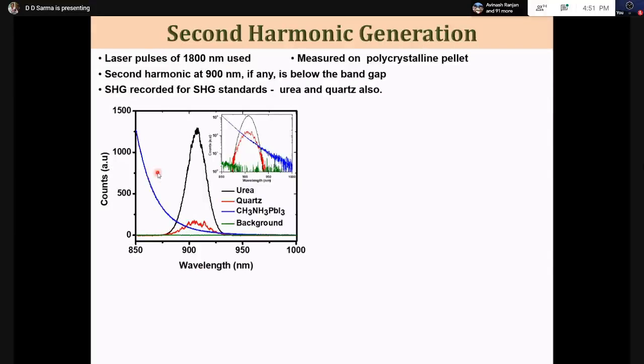Let me walk you through this. This is the response from my material of the second harmonic generation. What I'm doing is just counting the number of photons coming out around the 900 nanometer wavelength where I expect a peak to be. You see that when I use urea, which is a well-known polar material, I find this beautiful second harmonic peak. Quartz is also a polar material, but less efficient than this. This also shows me a peak. So I know exactly what the width of the peak is and where the peak should be if it is a polar material. My material is here, which has some huge intensity, but no peak here.